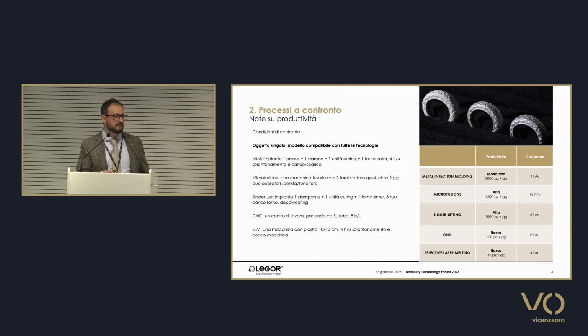The cycle of 2 days: the first day can be used for the printing of the object, and subsequently the sintering is to be performed, which can take as much as 10 to 15 hours with the different steps from green to brown to sintering itself.